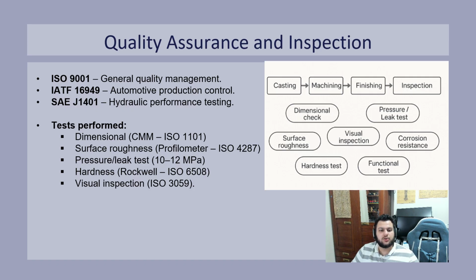The surface roughness testing with profilometers verifies the required Ra values under ISO 4287. Pressure and leak testing at 10 to 12 megapascals confirms the sealing reliability. Hardness tests per ISO 6508 ensure the correct material treatment. Finally, visual inspections under ISO 3059 identify any surface or coating defects. Together, these ensure each caliper meets the structural, functional, and safety standards before leaving production.